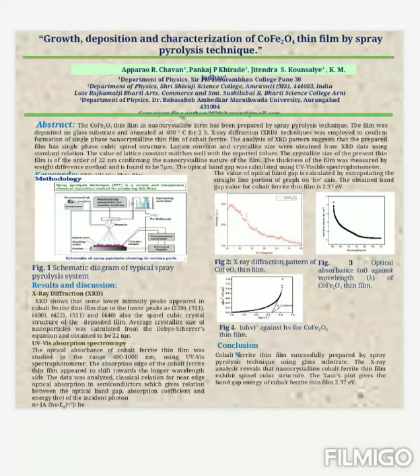Then again, figures 3 and 4 can be seen here. Figure 3 shows the optical absorption against wavelength of cobalt ferrite thin film, and figure 4 is calculated by the Tauc plot. It is measuring the band gap energy of cobalt ferrite thin film. The optical absorption of the cobalt ferrite thin film was measured in the range of 400 nanometer to 1000 nanometer using UV spectrometer. The absorption edge of the cobalt ferrite thin film appeared to shift toward the longer wavelength side.